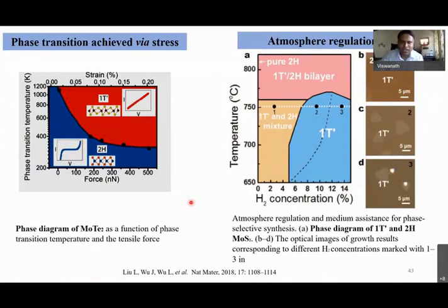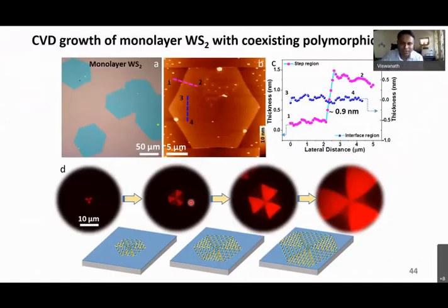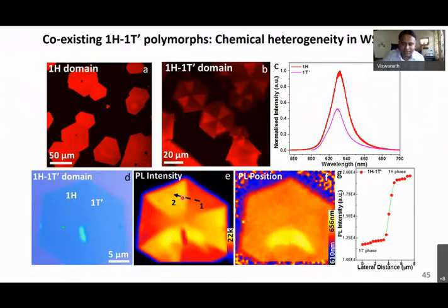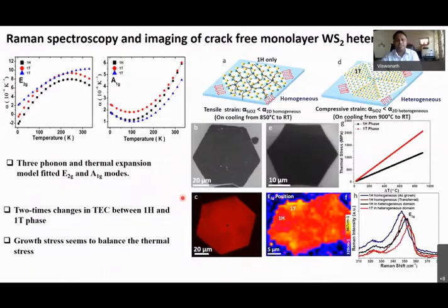There is some understanding, I would say more than understanding, there are lots of questions very similar to vanadium dioxide. You can see here coexisting allotropic phases can be captured using the fluorescent microscope. Having the same thickness in a monolayer form, you can actually manipulate the phases. There are several methods probably discussed.